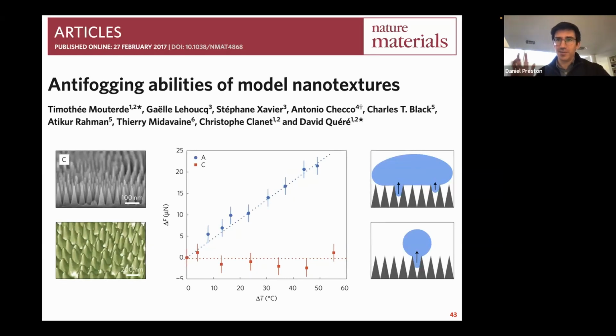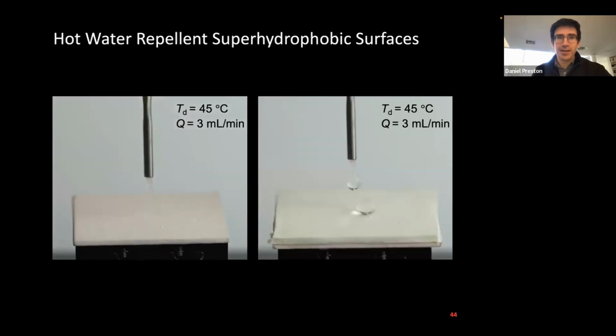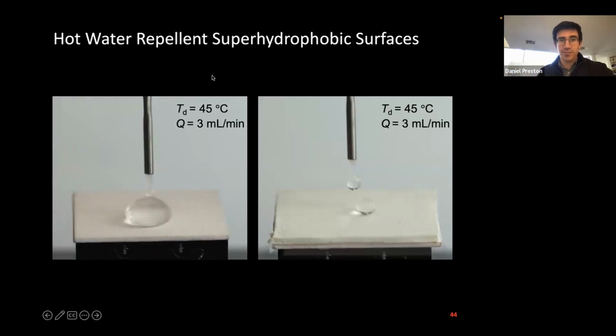It's a little bit challenging to make these really well-controlled, ordered structures at scale. And so in our case, we're trying to use these spray-on coatings to keep it scalable and make sure that it can be used in real-world applications. But we get this problem on the left, where we get these pinned droplets as the water temperature is elevated compared to room temperature. And we wanted to overcome that.